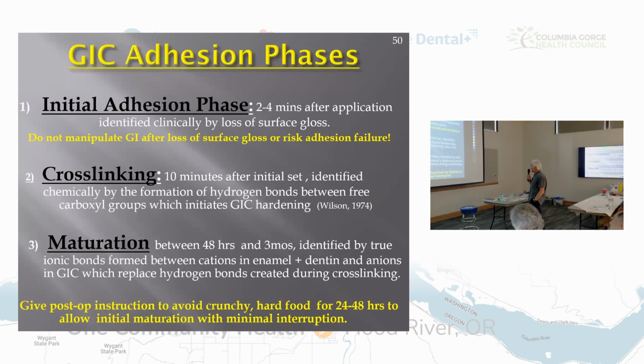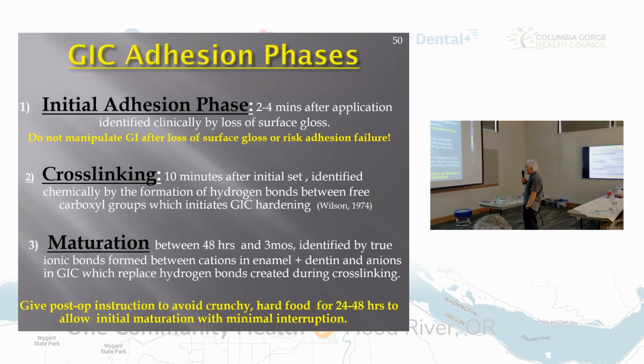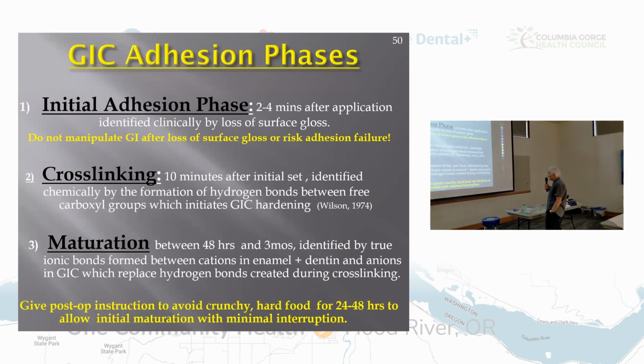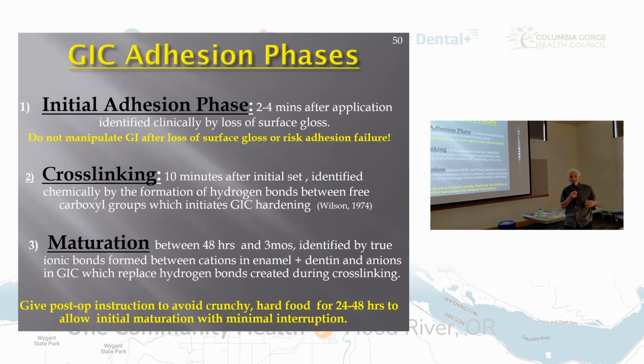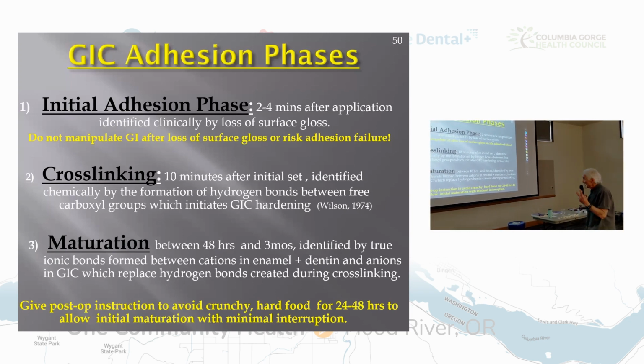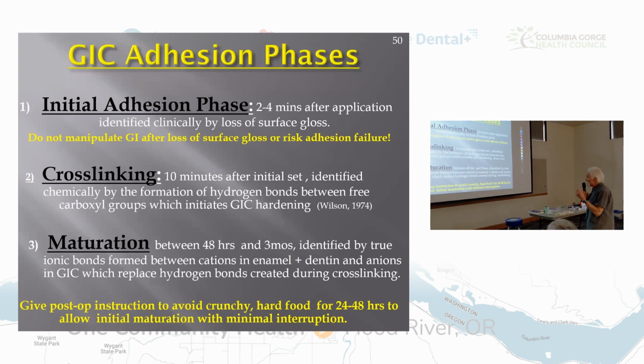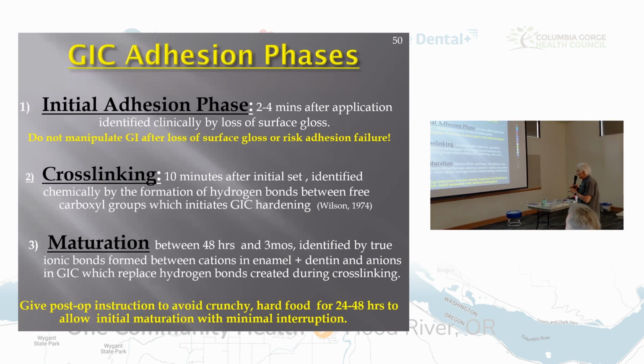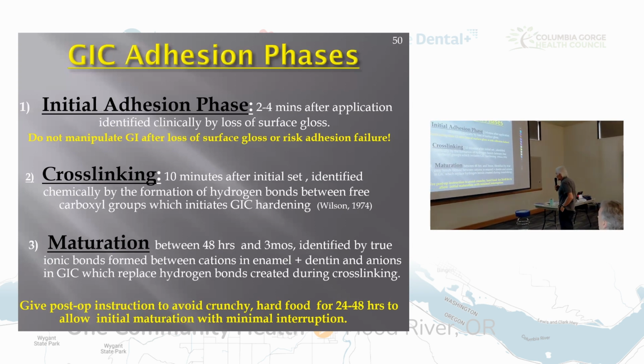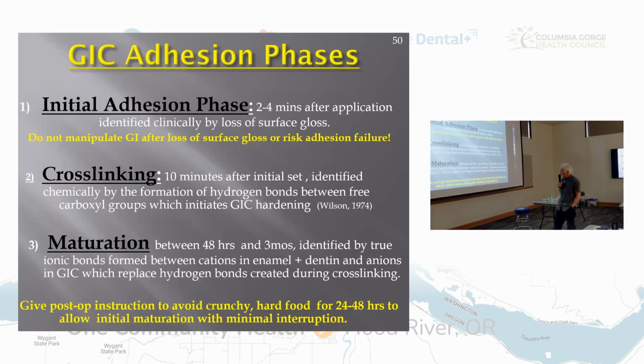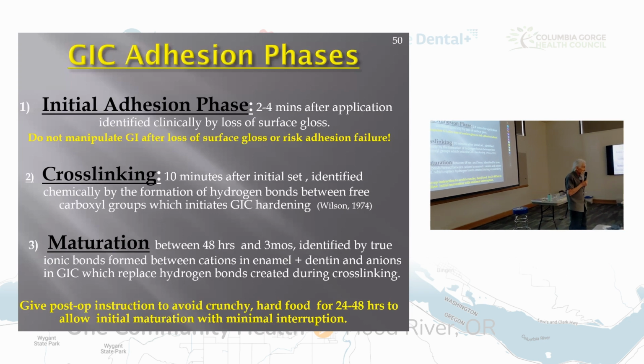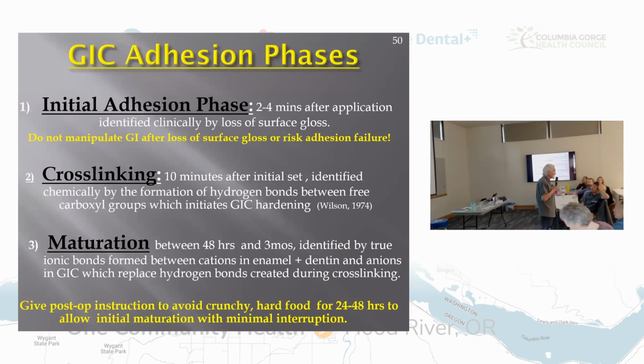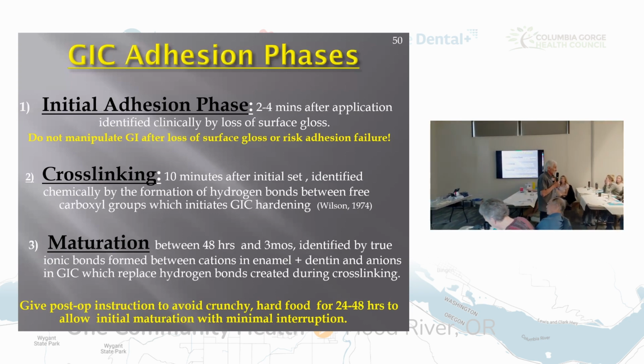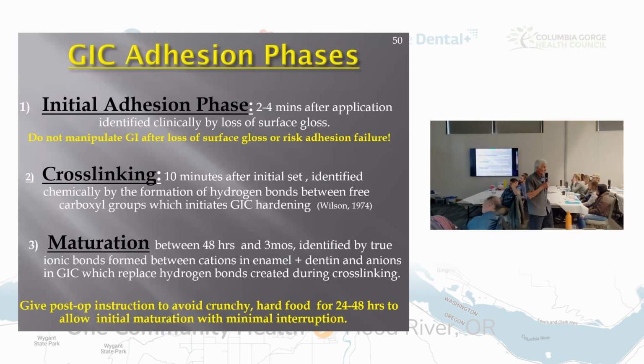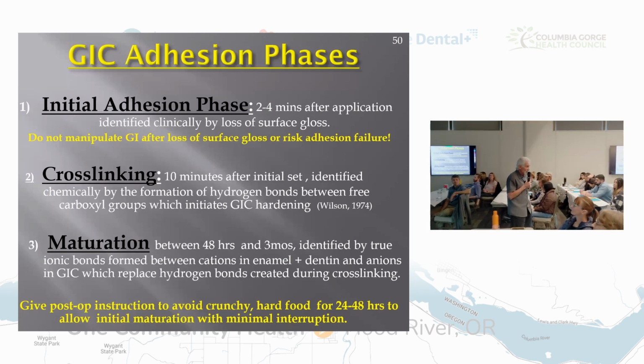Cations in enamel and dentin, anions in glass ionomer, which replace the hydrogen bonds created during the second phase, which is called cross-linking. You've got to give those post-op instructions to avoid crunchy, hard food for 24 to 48 hours to allow initial maturation with minimal interruptions. And then after that, you still got to wait another 3 months. This stuff matures over time and it gets harder. Next, please.